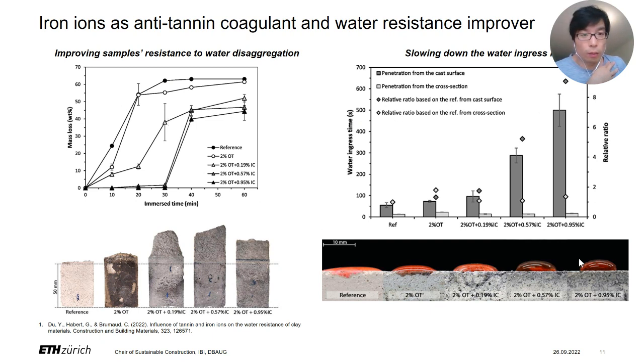We also did some tests about water ingression. On the right, we test the ingression time of a droplet into the sample. After using this mixture, it is more difficult for the water to penetrate the samples. So in short, we can conclude that oak tannin combined with iron chloride can protect the sample internally and externally. The internal protection is to increase the sample resistance to water disaggregation, and the external protection is to slow down the water ingression.